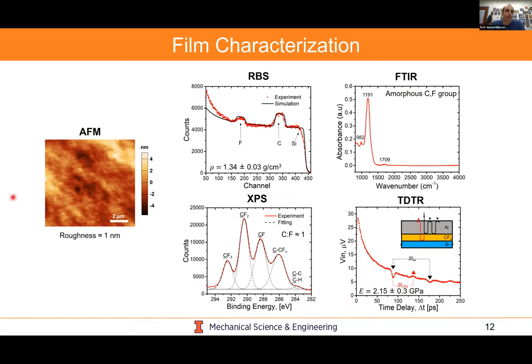So in this case, we do AFM to characterize roughness of the films we develop. We do RBS to get things like density of the films. We do FTIR to see the bonding of the amorphous groups, the carbon and fluorine of our fluoropolymers. XPS to see the actual chemistry, whether we have CF bonds, CF2, CF3. And then a process called TDTR, time domain thermoreflectance, to see thickness, thermal conductivity, as well as parameters like Young's modulus, which we could get from the acoustics of the reflectance within the film itself. And these now allow us to form a subset of characterized processes so that we could develop a mechanics model to understand what's happening.